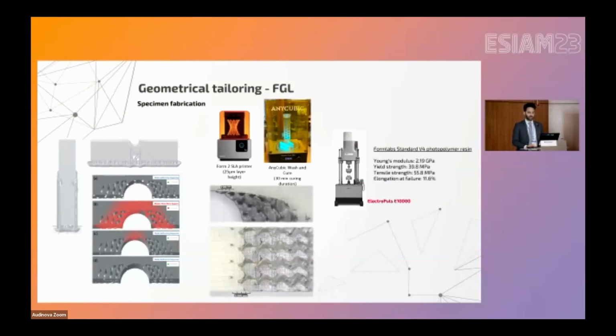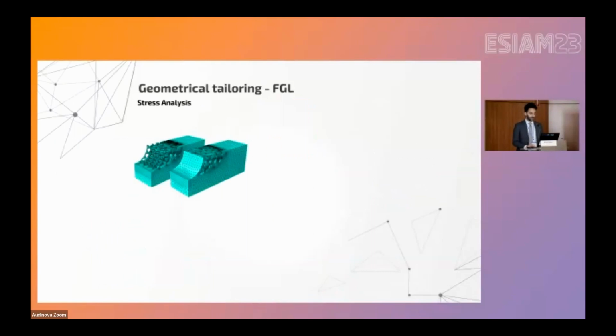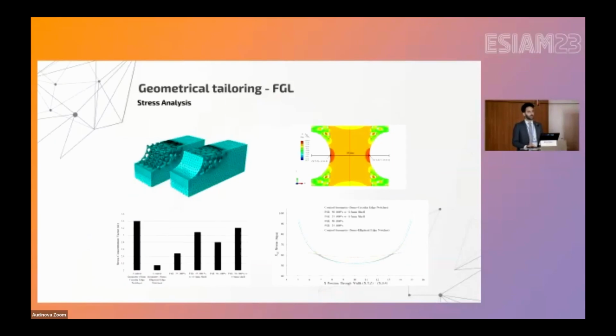They were made out of this material with the mechanical properties that you can see, and then tested using an Instron machine. At the same time, we performed some simple stress analysis to see how the stress is varying. As expected, we could see that the stress at the component is being reduced. Not to the elliptical case, obviously, but lower than the semicircular specimen. We had up to around 30% reduction in stress concentration factor.